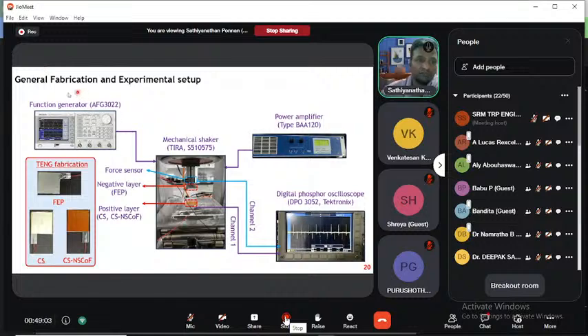So this is the fabrication setup. You can see how we fabricated it. After cutting the CS film, this is the neat chitosan and this is the chitosan CS film, and we attached it onto an acrylic disc on the backside of the aluminum electrode, and then connected a wire for electrical contact. Similarly, we fabricated the FEP. FEP is a synthetic polymer used as the negative material.